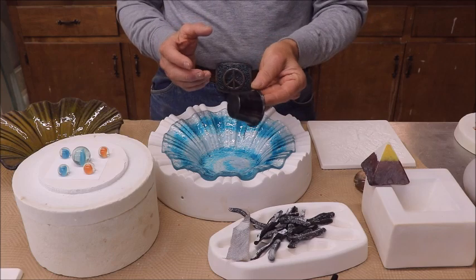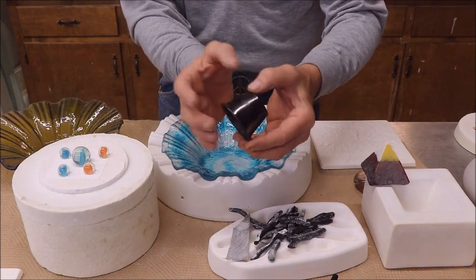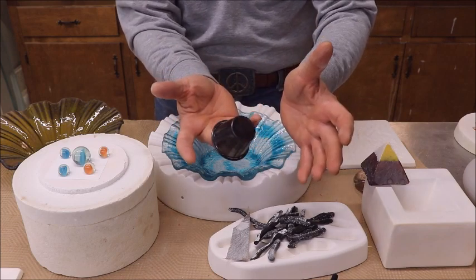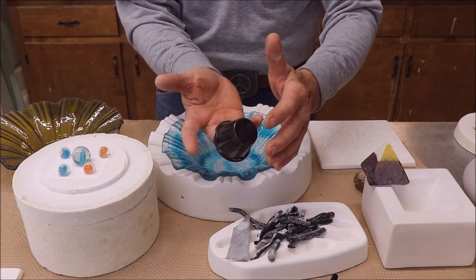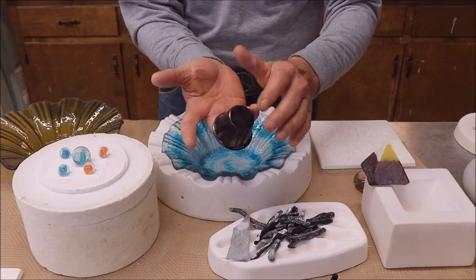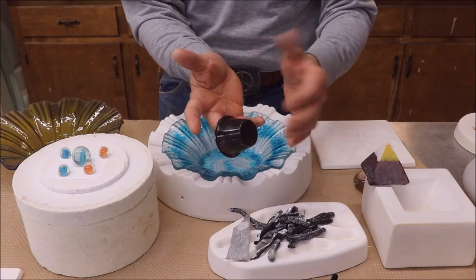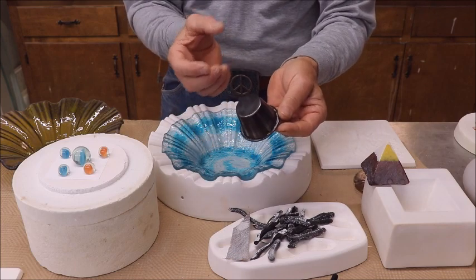Next: if you have stainless steel — this piece has been fired and the glass separator did not adhere properly, probably because it wasn't cleaned properly. It was lifting in a few places. You should burnish stainless steel before applying anything — whether boron nitride or any universal mold release. Take it to a grinding wheel with a wire brush, which you can pick up cheap at Harbor Freight. Now it's prepared to accept the mold release of your choice.